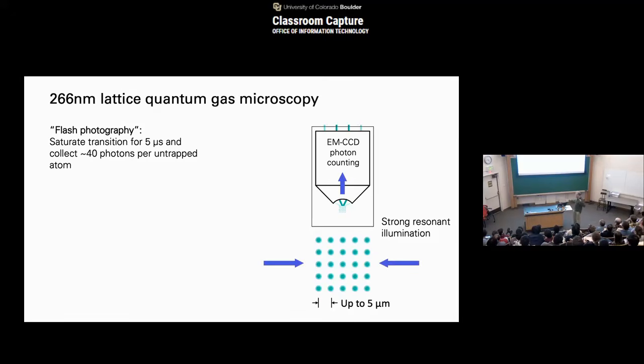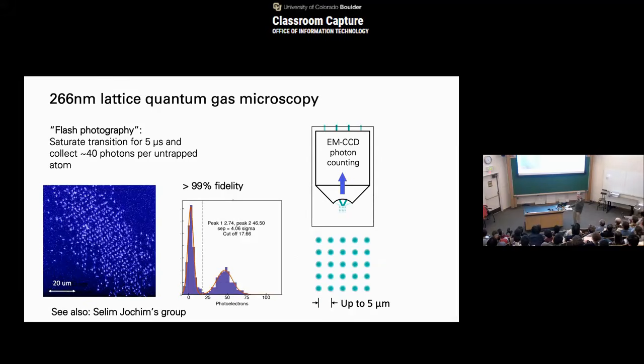We essentially do flash photography. We shine a lot of resonant light onto the atoms, totally saturating the transition. It's actually similar to what Junier is doing in strontium here. But here we can then resolve all the individual atoms very reliably with 99.8% fidelity or so, within only 5 or 10 microseconds of imaging time. So that is quite useful.